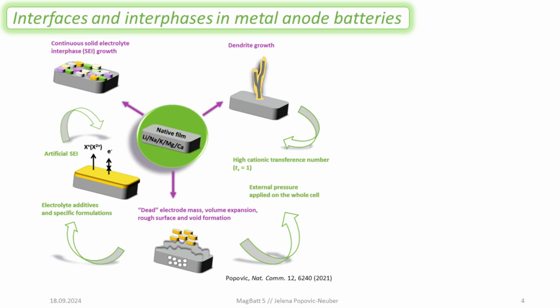These are non-thermodynamically stable materials with almost anything in contact. So we will have a consumption of electrolyte and simply end up with a dry cell after a period of time, after we've reacted all of our interfaces. Then in some cases, we have this dendrite growth. This is why the first lithium metal batteries were retracted from the market.